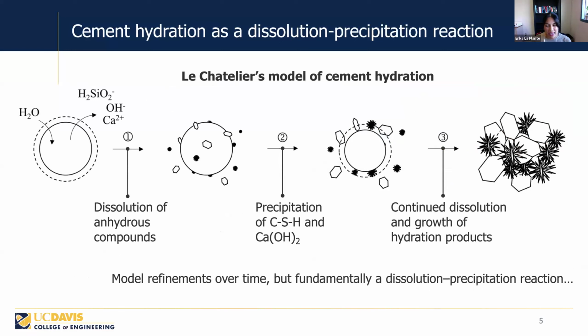So this idea of a dissolution-precipitation reaction emerged a very long time ago. This is Le Chatelier's model of cement hydration, which represents the dissolution of the anhydrous compounds as the first step during cement hydration, which then changes the pore solution composition. You have the precipitation of CSH and calcium hydroxide occurring after that, and then the dissolution of the anhydrous compounds continues, as well as the growth of the hydration products. So eventually, if you do reach complete reaction, you'll have the hydration products in place of your anhydrous cement. There have been model refinements on this over time, but fundamentally it remains a dissolution-precipitation reaction.